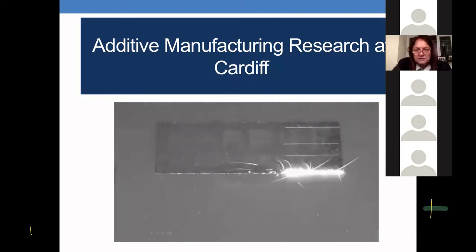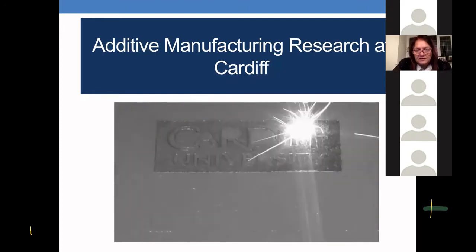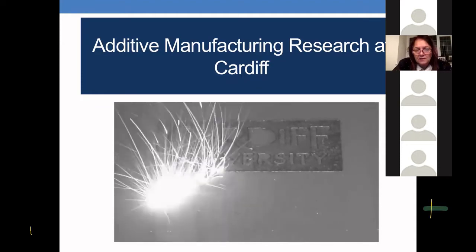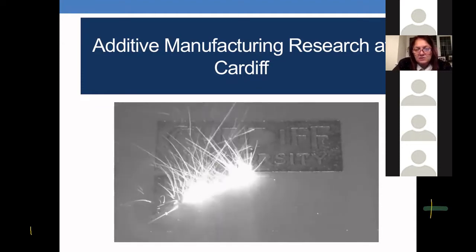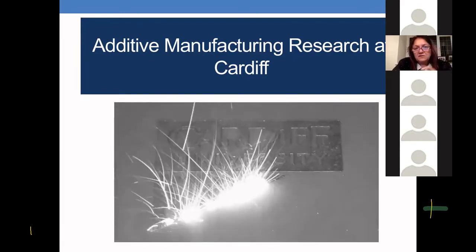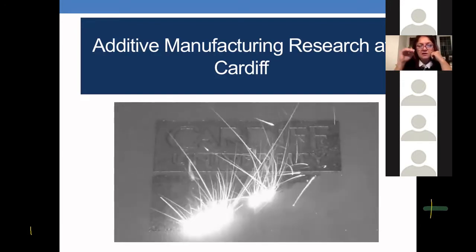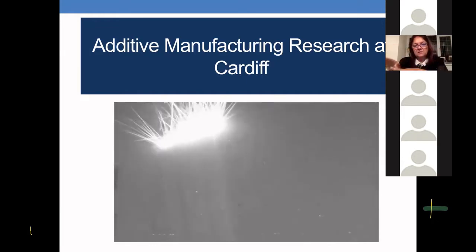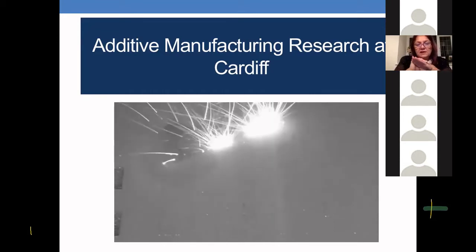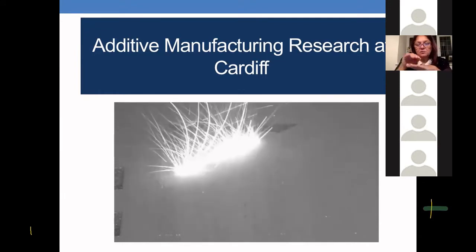What you can see is a video on a typical additive manufacturing process where layers of powder are put one above the other. So typically between 8 microns and 20 microns is the thickness of the layer, so layer by layer. And then the laser actually scans the surface, and the process is called selective laser melting because the laser goes to points selectively, which obviously correspond to the